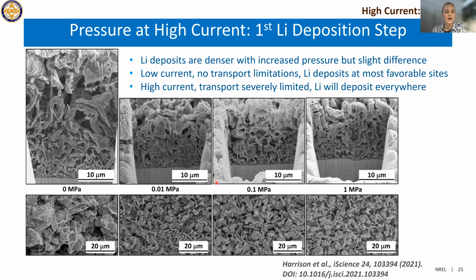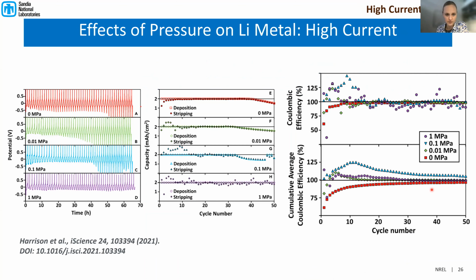and it has a lot of these pores intermixed. And so what we understand is that for high current density, there are really some transport issues. And so the lithium just deposits everywhere it can, instead of forming those nice big lithium grains that we were seeing at the low current. And so this pressure did not solve the issue for the lithium morphology under high current conditions.